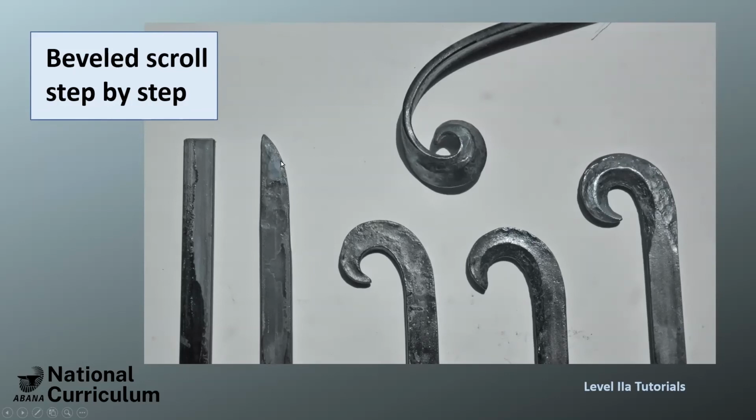Then you bend this over to the straight side. I did a couple tests, and I got to, this needs to be bent over about a 3/4 of a total bend, so it's 270 degrees. Then you start beveling the inside with a rounded hammer. I have 2 rounding hammers, and I use the smaller one for this. And as you can see here, while you do that, it opens up a little bit.